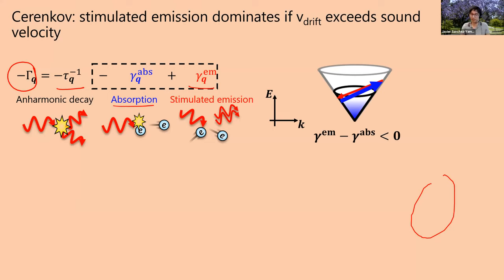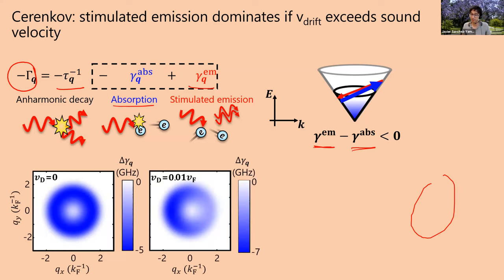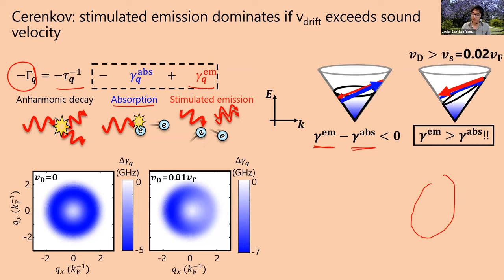And it turns out that if you think about this process of emitting phonons and absorbing phonons, the emission is going to be much less than the absorption if you don't apply a drift velocity to your electronic system. But if you do apply a drift velocity to your electronic system, it tilts the Fermi surface. And when you tilt it enough so that the drift velocity exceeds the sound velocity of your material, then it turns out that emission of phonons becomes more efficient than absorption. You get more emission than absorption.